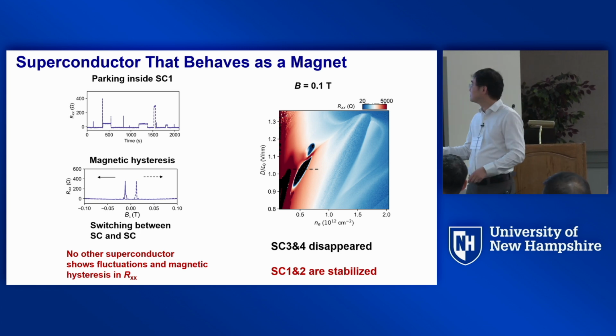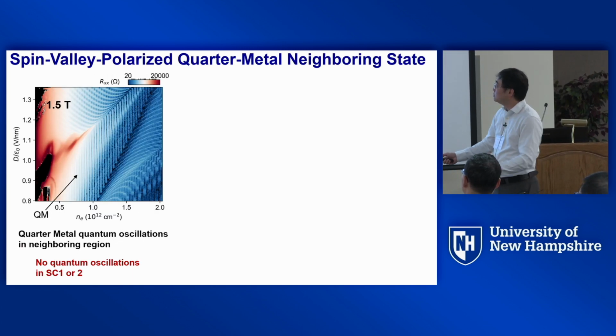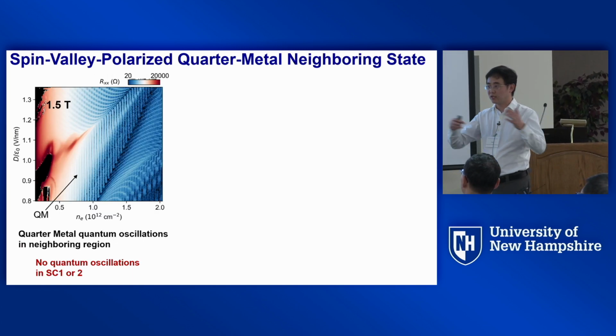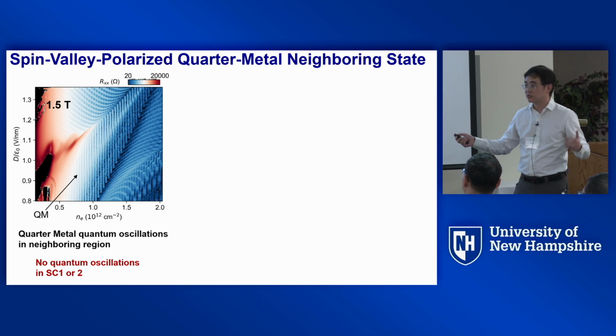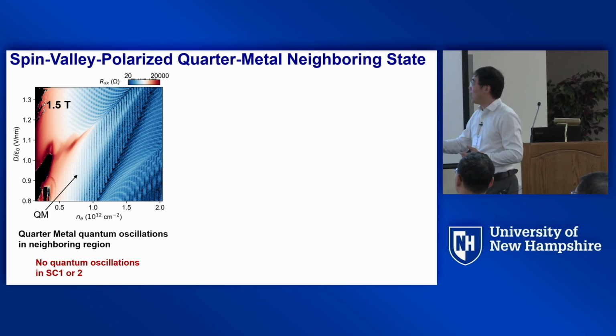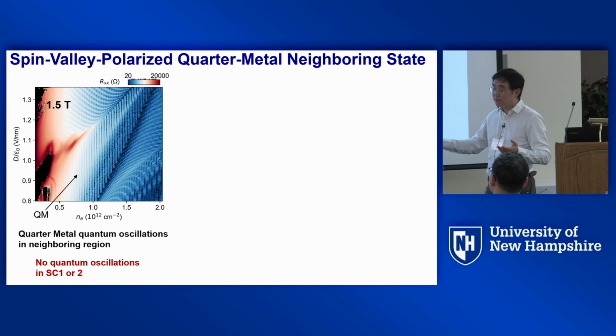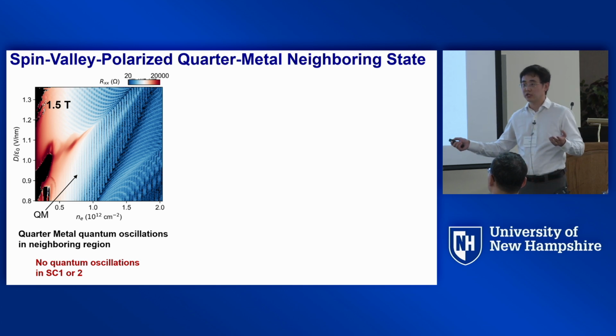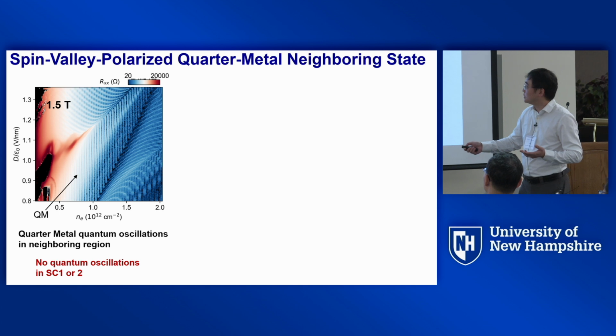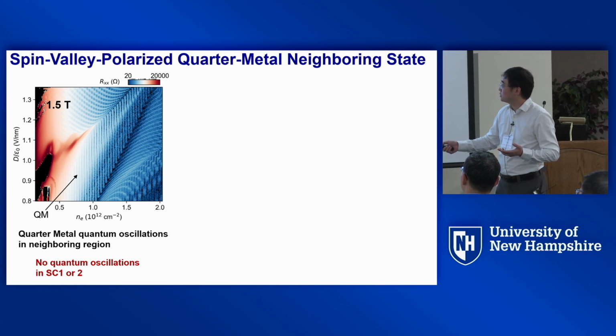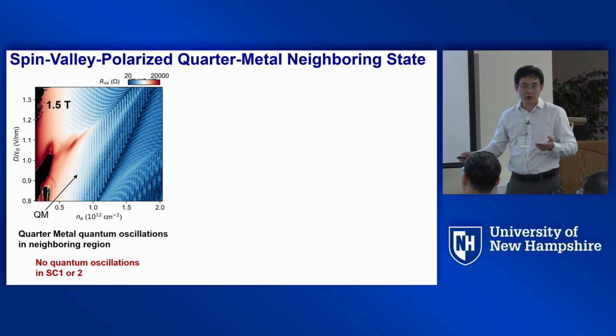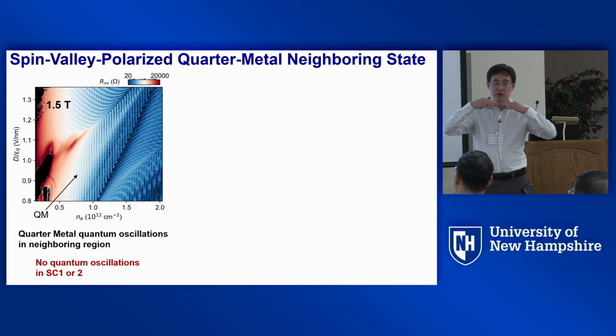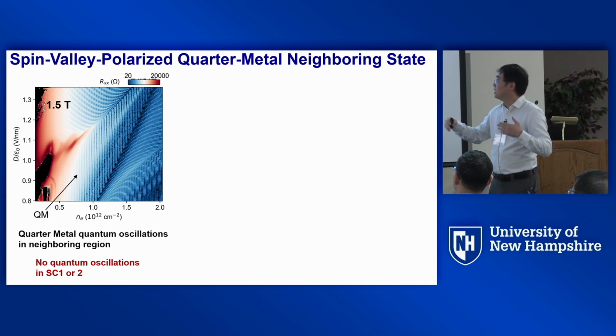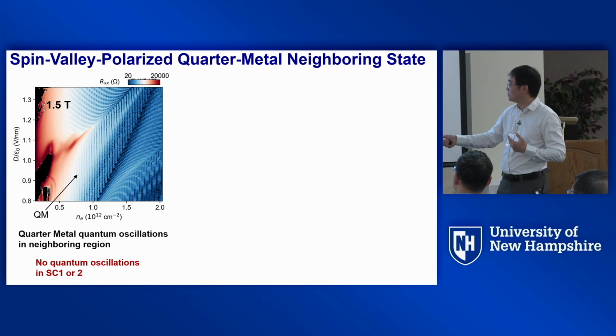That's right. Okay, now let's move on. We want to understand what is going on at the Fermi surface. The first thing we did is to apply an out-of-plane magnetic field of 1.5 Tesla and measure the quantum oscillation. What you can learn from the quantum oscillation is, based on the density of electrons from one peak to another peak, you can tell the degeneracy of your Fermi surface, okay? And I will tell you what that really means later.